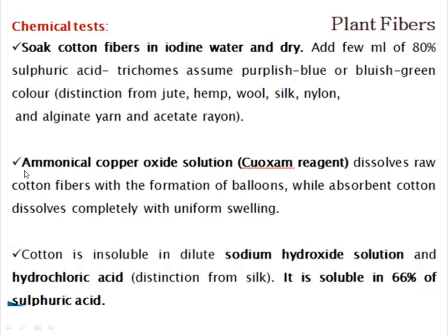The next chemical test for cotton fiber is treatment with ammoniacal copper oxide solution, also known as Cuoxam reagent. On treatment with Cuoxam reagent, the raw cotton fiber dissolves with the formation of balloons, while absorbent cotton dissolves completely with uniform swelling.